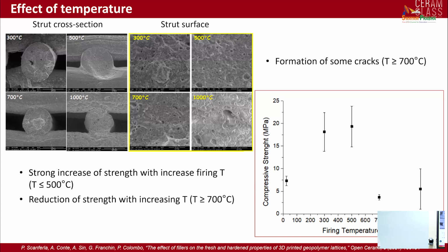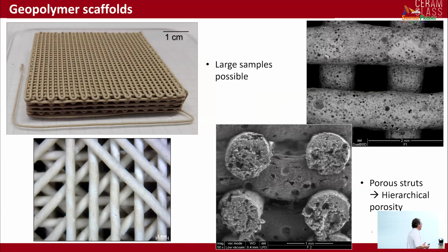And the material starts as inorganic, but the mesopores start closing and you obtain a dense matrix. And with increasing temperature, we found that we had a decrease in strength due to the formation of cracks induced by the crystallization of the material. We can make large samples. We also worked on making porous struts in order to allow for the media, like gaseous or liquid media, to enter into the structure and interact with the geopolymer.